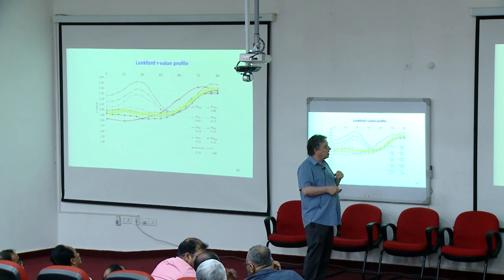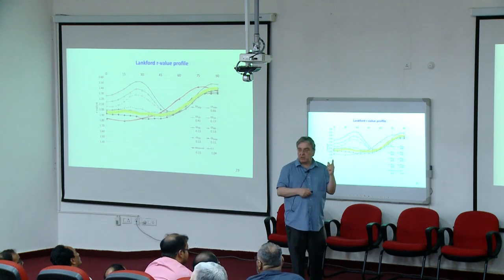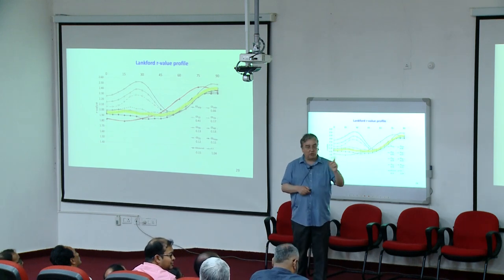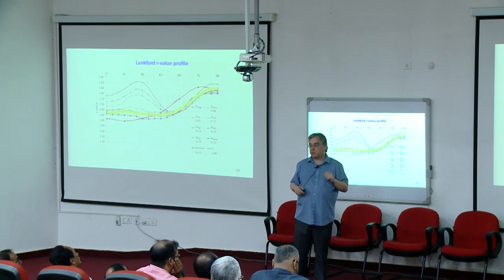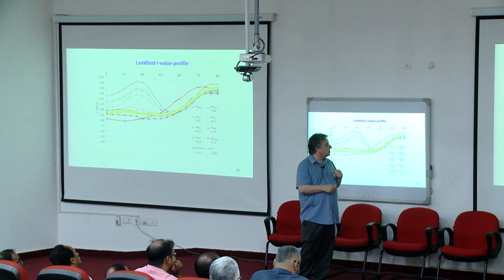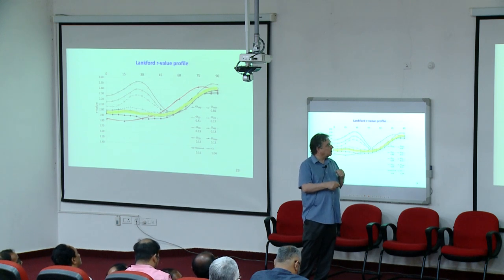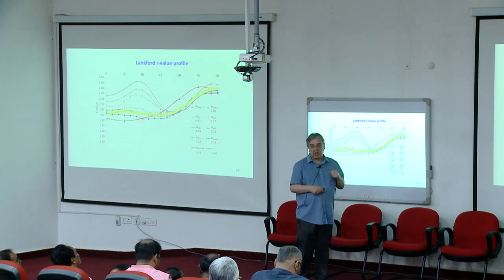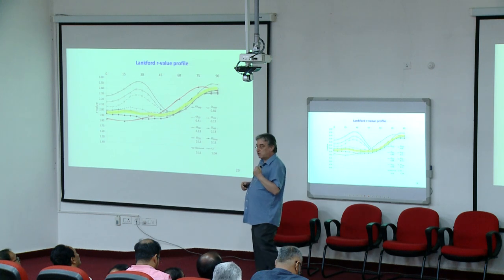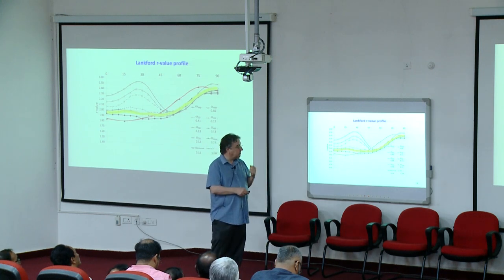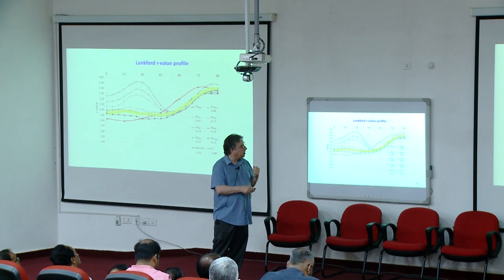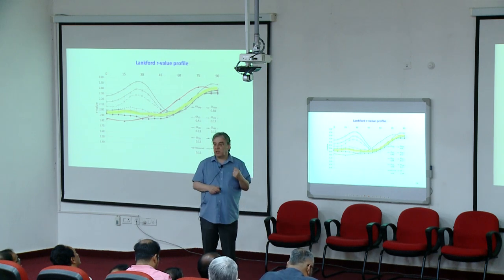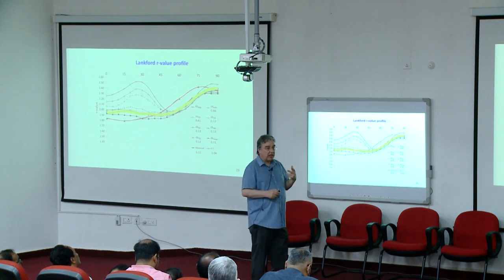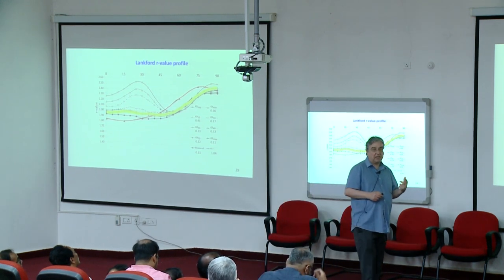What this shows you here, on the vertical axis, is the R value. This is for steel, not for aluminum. The first example that I showed was for aluminum, where you had this typical V shape. Here, steel has a different shape. You have what we call a six-ear behavior. By the way, you can see that the R values for steel are much higher than for aluminum. The R values for steel, in this case, go from 1.8 to even higher than 2.5. That's why steel, in general, has a much better deep drawability than aluminum.